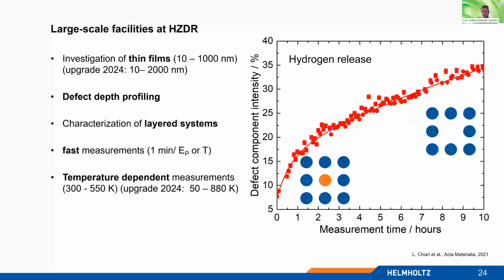Another point we investigated due to these fast measurements were the changes in materials loaded with hydrogen. So here you can see what happens if the material was loaded with hydrogen and what happens over about 10 hours. And as you see, the defect component increases due to the release of the hydrogen, and therefore the vacancy becomes visible again for the positron. And so we see an increase in this lifetime.